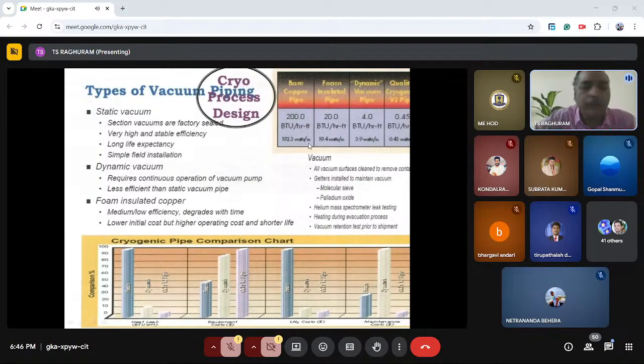Of course, the diameter of the pipe is important. Based upon that, the approximate heat leak into the pipe will be 192 watts. A very large number, right? So, when you use foam as an insulation, 1/10 of that can be cut out. That 192 watts can become just 20 watts, right? Around 19.4 watts per meter.